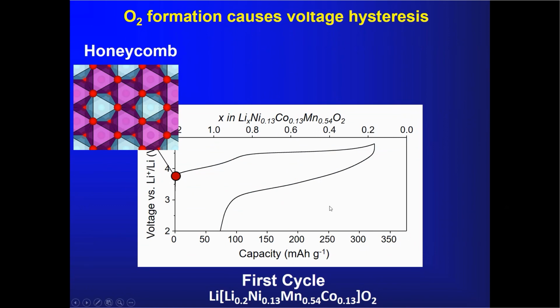So with all of that evidence together, we see molecular oxygen, we see disordering, we see an irreversible structural change. What do we think is happening to explain all of this? So here's our plan view of our pristine material with the nice honeycomb structure. The lithiums are in the octahedra in blue here, oxygen's in red, of course, and we've just represented all the transition metal ions in one color to make it simpler, in purple. So here's the structure of the pristine material.